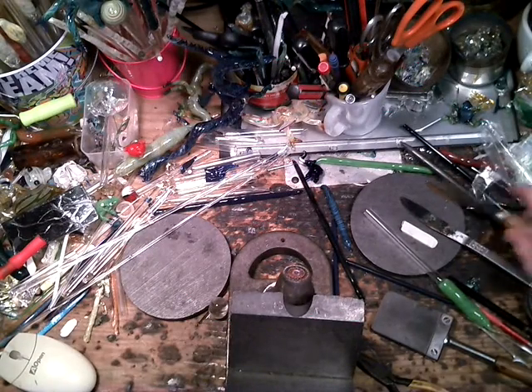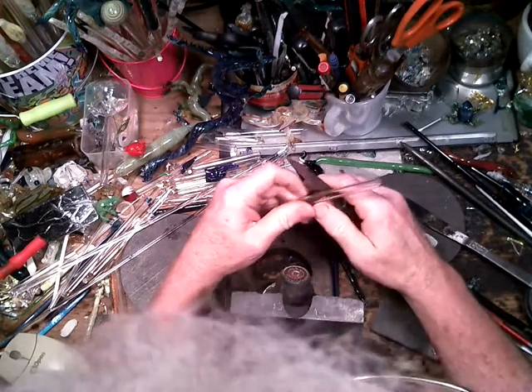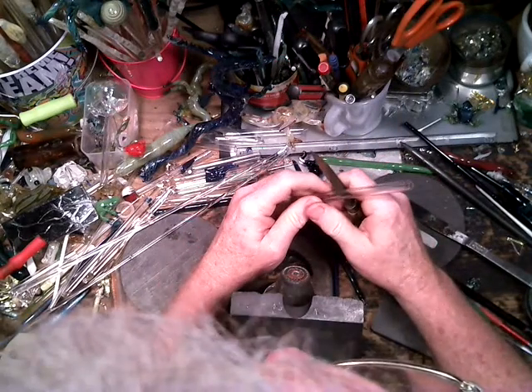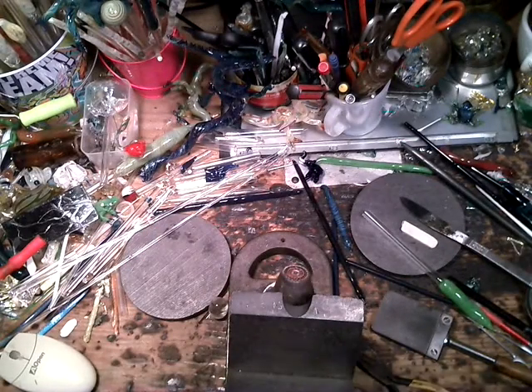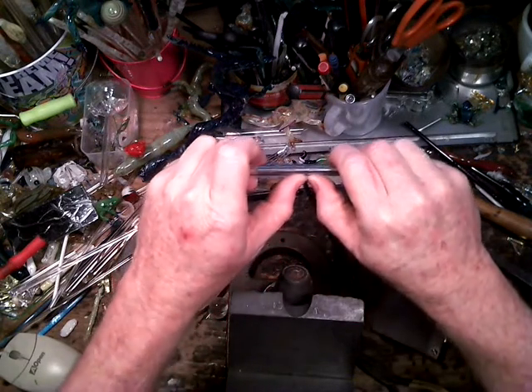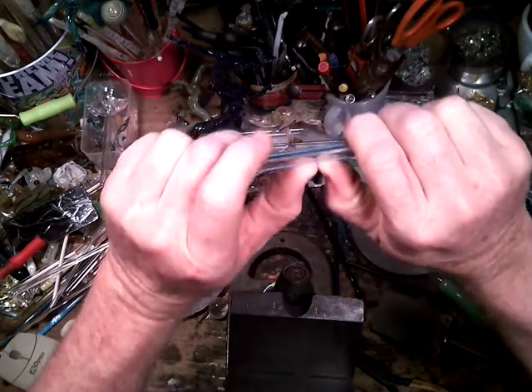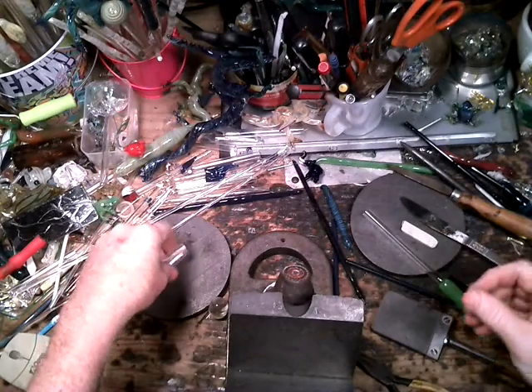One of the simple tools that is good to have in your glass repertoire is a scoring knife. What it does is you can cut tubing and rod to certain sizes. First you press firmly and scratch it, and you're going to hear a scratching noise. You then lick your finger and wet the score, or if you have some water handy, wet it. Put your thumbs at 6 o'clock or 12 o'clock, with the score exactly opposite, and press away. It gives you a nice clean snap.